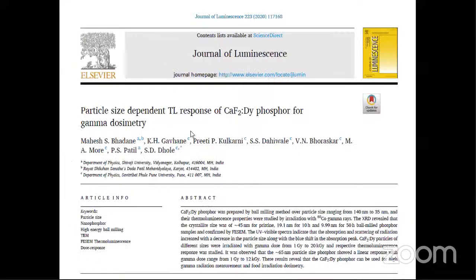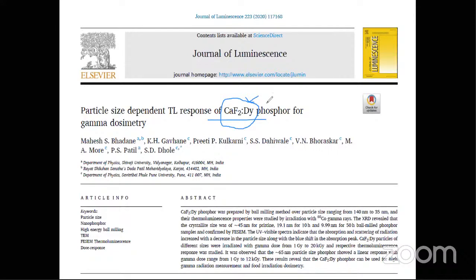So I will explain our paper and then stop today's lecture. I have chosen here calcium fluoride dysprosium doped material. TLD 200 material, that is CaF2:Dy doped material, indicates 10 milligray to 100 gray only. But by using particle size dependent TL response, through the ball milling method, we have expanded the dosage response of the material up to 1 gray to 12 kilogray. In this article, we reduced the particle size using the ball milling method. I will explain in the next slide.